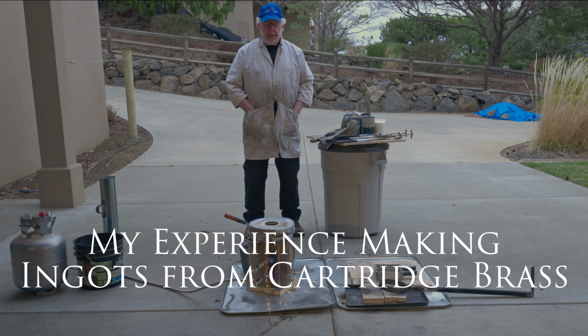I use a tube to pour the cartridges down into the crucible, as it's so easy to spill them all over inside the furnace, and this method is way better for your hands. While there is heat coming up through the tube, your propensity to get burned is pretty low. Anyway, you can look down the tube, decide how much to put in, and you'll see that I fill it more or less to a heaping state, but try not to overfill. Here I'm a little light, and so I add a few more, and that's it. Time to put the lid back on, refire the furnace, and melt those puppies down.